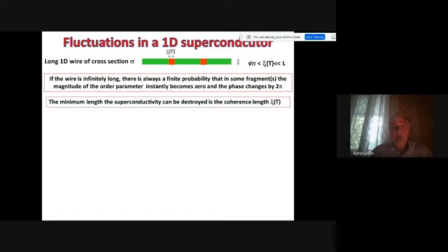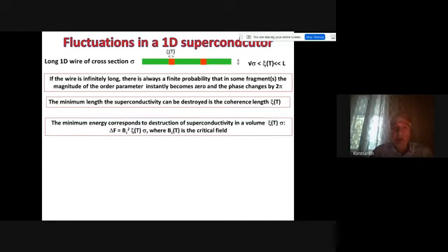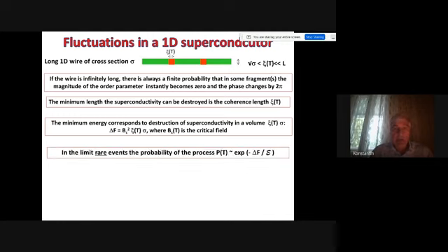Then in the old textbooks of superconductivity, it is written that if one wants to destroy superconductivity in some volume, and in our case the smallest volume has the extension of the coherence length, one should pay some energy, which is the condensation energy. And then theorists are capable of showing that the probability of such a process depends exponentially on this energy required to destroy superconductivity within such a red spot, normalized by some energy. And the whole story is about what this normalization energy is.